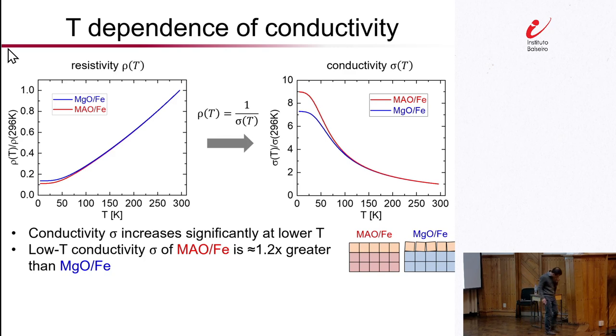So not too surprisingly, because we have a nice pure elemental metal film, the conductivity does increase quite a bit, going from room temperature to 10 Kelvin, by almost an order of magnitude. And you can also see that the conductivity is about 20% greater in the low temperature limit for the cleaner sample of iron on MAO. Also not surprising because it's a cleaner film, so we should have a smaller amount of residual resistivity coming from the defects.